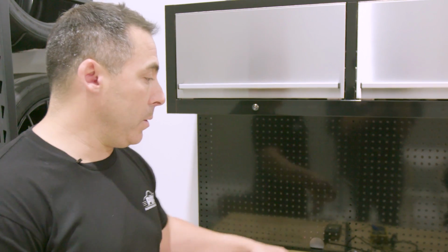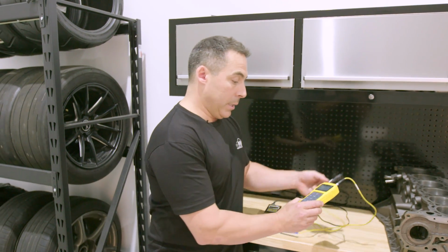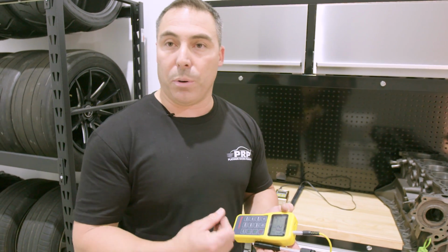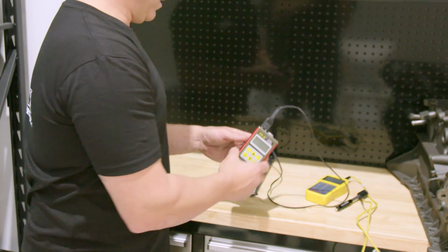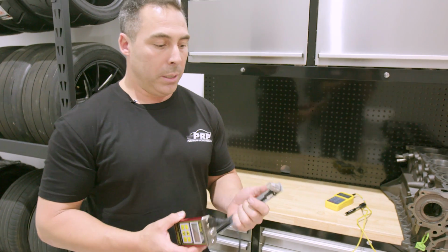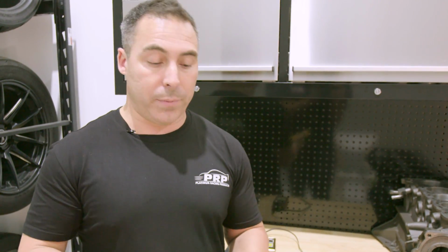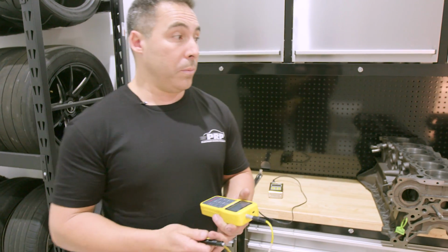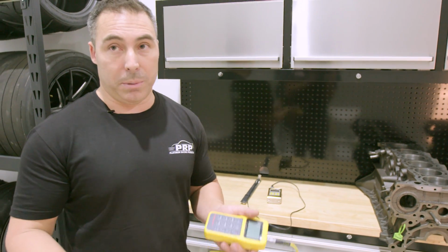So I use non-destructive testing, obviously. I have a little hardness testing machine. It bounces a ball bearing and measures the frequency, basically. This is a sonic tester. It's the one I choose. It's a dual crystal version. You don't want to compare one hardness test to another. As long as you're using the same piece of equipment and it's calibrated, that's all you need to worry about. I like to hardness test blocks in the same spot on all of them, just to give me some consistency.